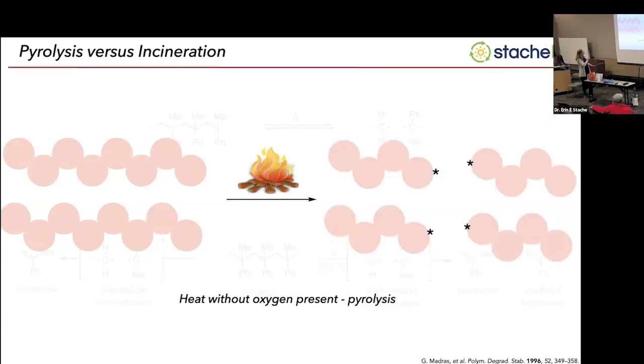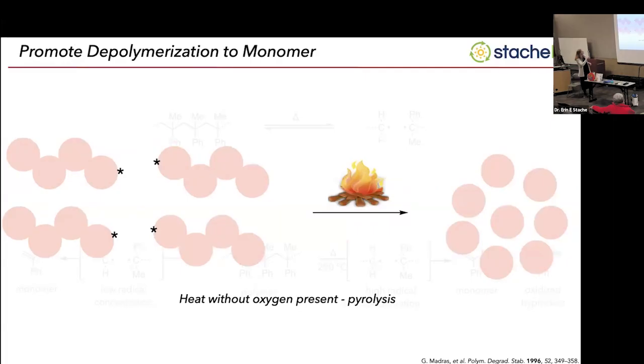Pyrolysis, if you heat the plastic without oxygen, you just start breaking it into smaller chains. And so you get these little, we'll say, reactive species, so they're very high in energy and they don't want to sit there. And they start to break down further with more heat, and you start to get back to the monomers. So pyrolysis and incineration are 2 very different things. They both involve heat, but one is with oxygen and pyrolysis is without. And so pyrolysis is the process by which we recycle polystyrene. Like I said, 750 degrees is a lot of energy.